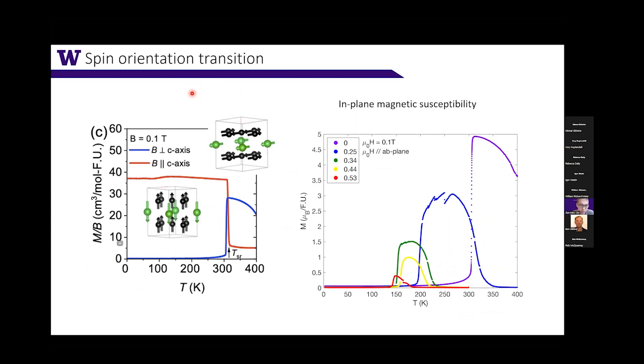Just recall what is being measured in the TbMn6Sn6. If you measure the magnetization with field in-plane, you get a large response below the ferromagnetic transition temperature, but a sudden decrease at the spin orientation temperature. For the field along the c-axis, you have the opposite effect, because now you have the opposite anisotropy. If you measure the in-plane magnetization of this chromium-doped compound, you get what you expected: the onset of the in-plane magnetization below the ferromagnetic transition temperature, then a sudden decrease at the spin orientation temperature, and the overall magnetization decreases as you increase x.